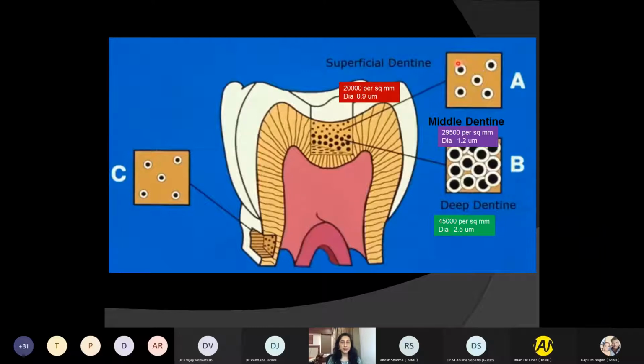And in deep dentine, can you believe, the dentinal tubule number is 45,000 per square millimeter, and the diameter also increases to 2.5 micrometers. And just see, can you see any much intertubular dentine present? So remember not to etch here at all. If you etch in deep dentine, you are going to harm the pulp, because these open dentinal tubules will lead the phosphoric acid inside the pulp.